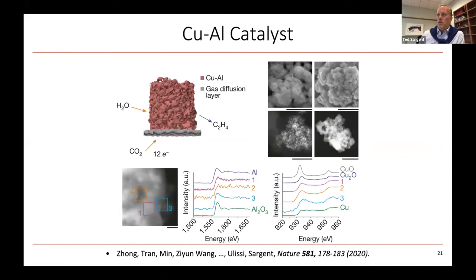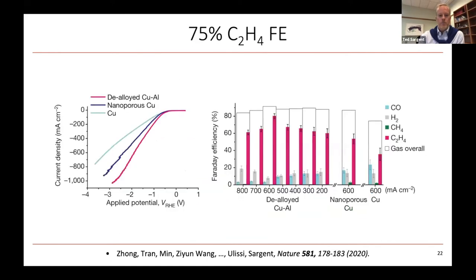So now there were aluminum rich regions and copper rich regions, did a selective etch where we, you can see here, we're developing a kind of nanoporous material on the 10 or 20 nanometer length scale, selective etch because we're able to selectively remove the aluminum, and end up with a mostly copper catalyst with an aluminum-rich surface and a lot of pores, and therefore very high surface area, one of the concepts I was talking about earlier for where nano can really help us.